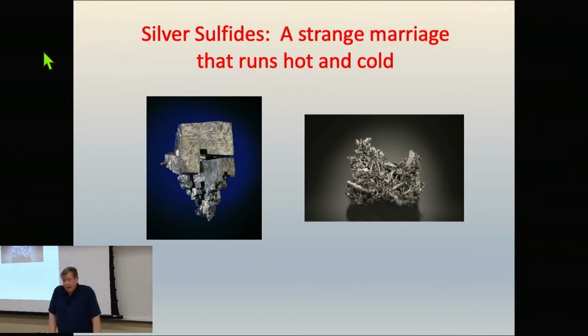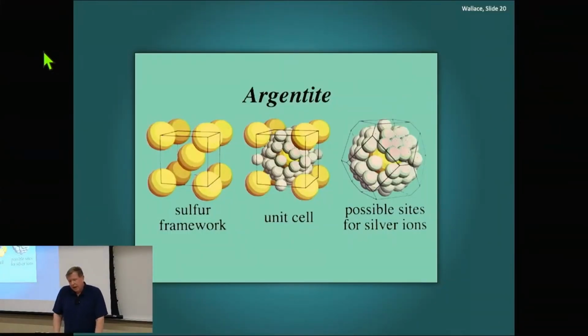And then on the other side, you can actually see a low temperature form. So it formed at a temperature, in this case, less than 170 degrees C, which is just the monoclinic form. So that's a piece from Arizpe. So those are the same chemistry, but they were formed at different temperatures, giving a cubic appearance versus an appearance that looks more like a Roman sword. If I was in a classical chemistry class and I asked you to tell me what silver sulfide looks like, you would first draw the sulfur framework. So we got some elements here, so it's silver 2, sulfur.